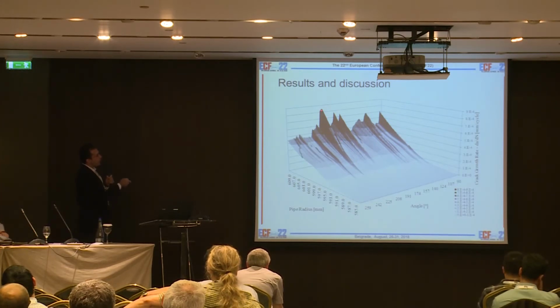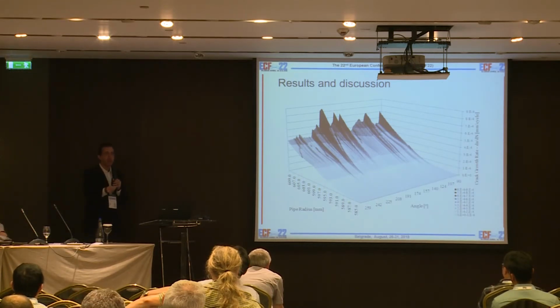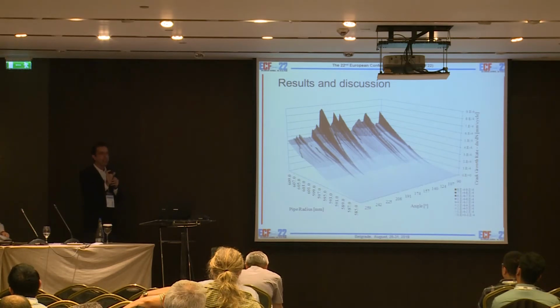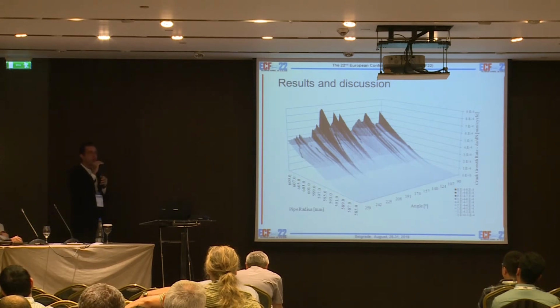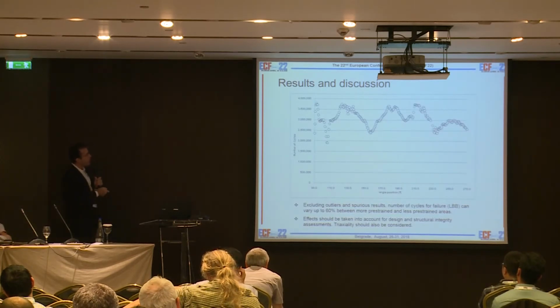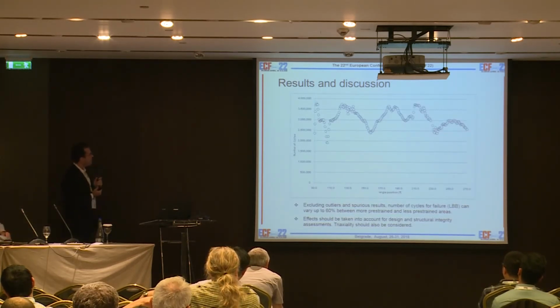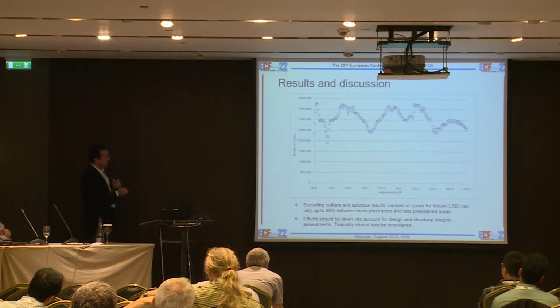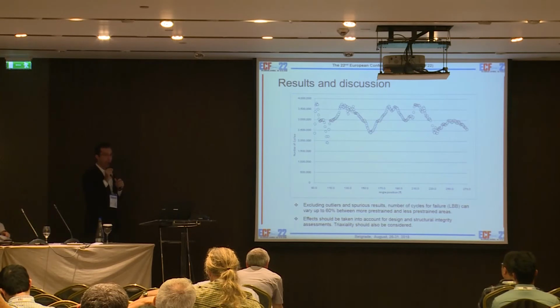So when we reach the outside of the pipe, in each position, we consider that the leak before break condition was reached. LBB was feasible in all conditions, but we did want to characterize, if the crack tip was positioned in every millimeter, what should happen when it reaches the outside portion of the pipe. So I'm bringing only one example of that. This is a graph that shows the number of cycles for the crack to reach the LBB condition depending on the angle position of the crack tip.